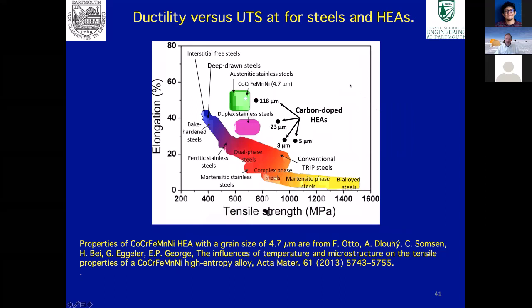And finally, on these materials at room temperature, you can see we've compared them here to the different kinds of steels in this so-called banana plot, where we've got elongation as a function of tensile strength for many different steels. And you can see these carbon doped high-entropy alloys actually have very good properties. You want to be up in the right-hand side here for the best properties.